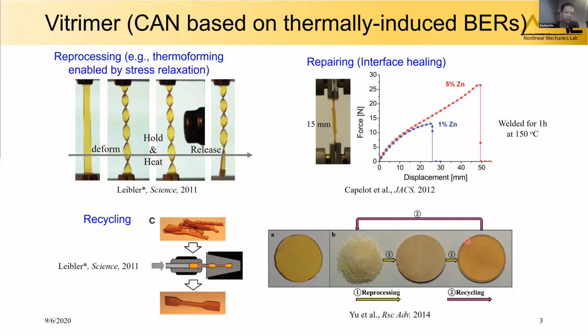So many different CAN materials have been developed. In 2011, the Leibler group developed a CAN material based on the thermally induced BERs. The Vitrimer has shown the capabilities of reprocessing, repairing, and recycling. For example, through a simple thermoforming process, a Vitrimer strip can be permanently reshaped. And for repairing, two Vitrimer strips can be welded together under heating. The Vitrimer can also be recycled. The broken parts of the Vitrimer can be recycled into new parts through injection molding.